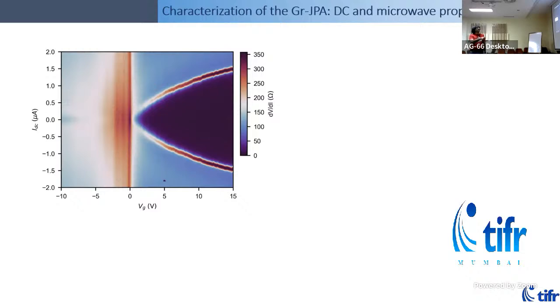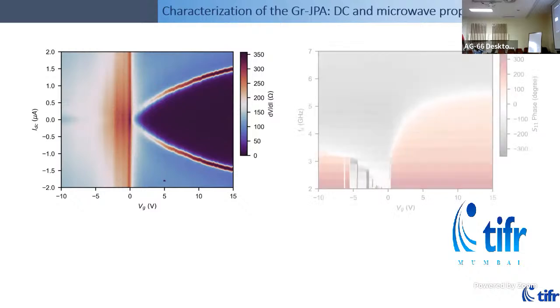In fact, on the hole side, it doesn't have any supercurrent flowing through, and that's primarily because of the way we make these Josephson junctions. We do some processing to increase the transparency on the electron side. It actually makes them quite terrible on the hole side. This asymmetry was also seen in the data that I showed you. So the amount of critical current is tunable with gate voltage. That's the tunability part.